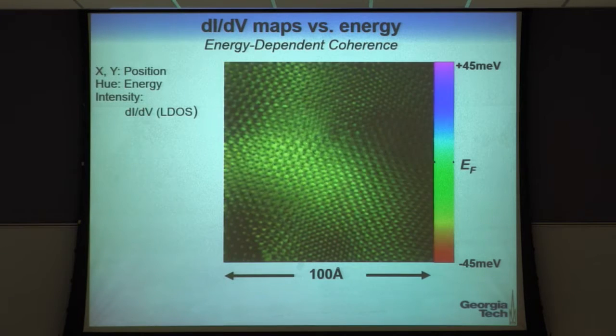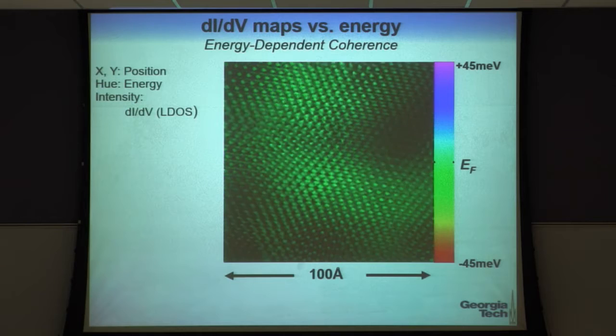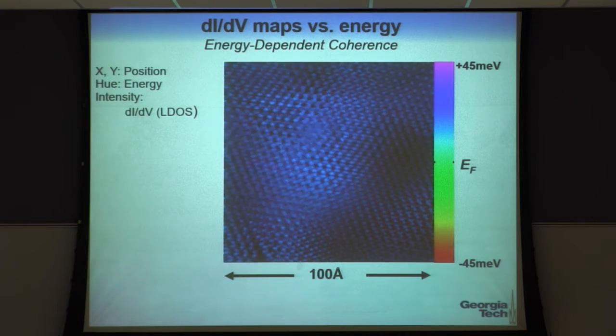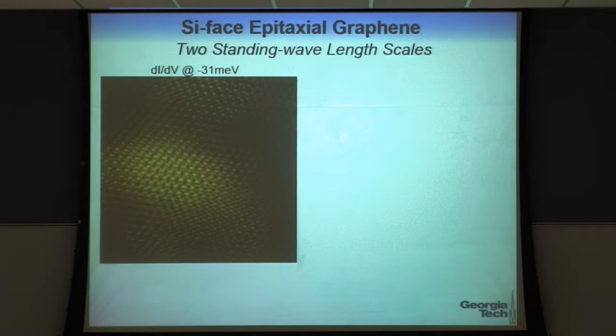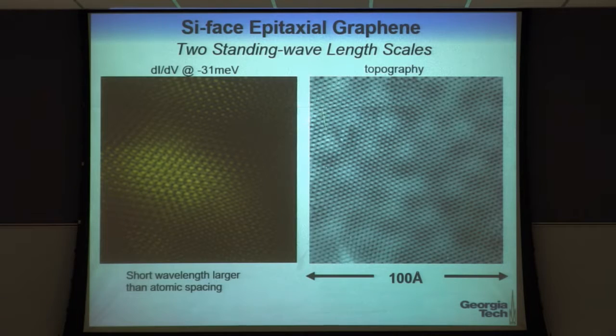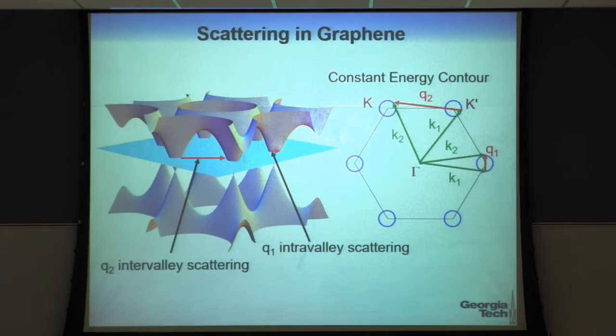the electron waves, okay? And you might think, well, those dots there, those are atoms in the graphene, but it turns out that they're not exactly atoms in the graphene. Here's the topography. So you can see the atoms, the atomic structure. The structure there is not exactly the same. And it's not the same because these really are the standing wave patterns that we're seeing. They're created by having electrons near the Dirac points.